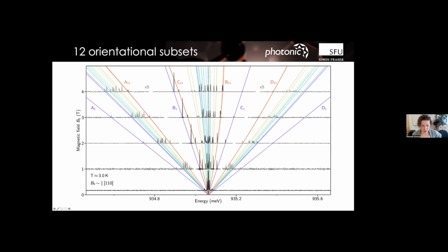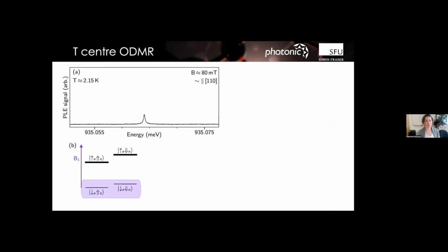You start off at 0 field, everything's one really nice, ultra sharp single peak. And then you split that all out and you can actually pick which orientation you want to talk to. And here we've color coded the different orientations with the A, B, C, D transitions for each of them. We say 11, we actually have 12 here. You just haven't quite broken out this level here, this A, B, C, D, that one actually has 2 contributions to that signal, which you could guess by just looking at it. So yeah, quite a bit, but you can go and take a look and then do spectroscopy on each of those centers.